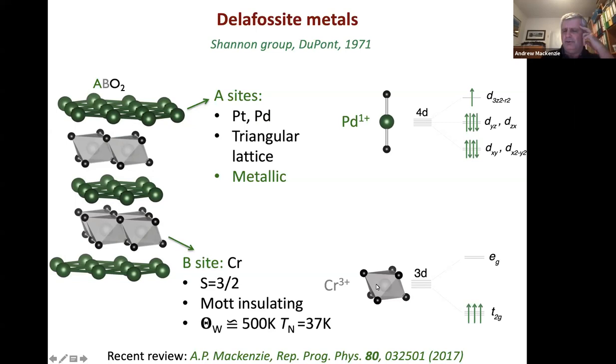That is not the case when you put in chromium instead of cobalt, because it's also 3+, but it's sitting there in the 3d3 configuration in the high spin state. So if you do just a simple non-magnetic band calculation, you would believe that the chromium oxide layers contained the Fermi level, that it sat in the chromium-based conduction bands. That isn't what happens. There's plenty of spectroscopic and transport evidence that the chromium layer is Mott insulating, and it forms below about 37 Kelvin a 120 degree, or at least roughly 120 degree, antiferromagnet, with the spin 3/2 that you'd expect of the high spin configuration of 3d3.